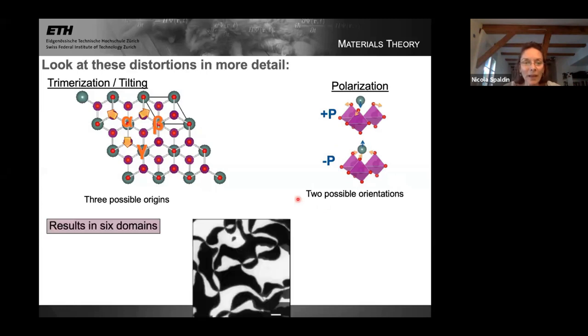And if you were looking very closely at the very first slide, when we were looking at the electric dipole pattern embedded in the cosmic microwave background, you may have noticed that always I had six, one, two, three, four, five, six domains meeting together at the intersection point, which in three dimensions is the one-dimensional string. So just by the simple hand-waving inspection of the crystal structure, I start to be able to understand this ferroelectric domain structure, which is extremely unusual.